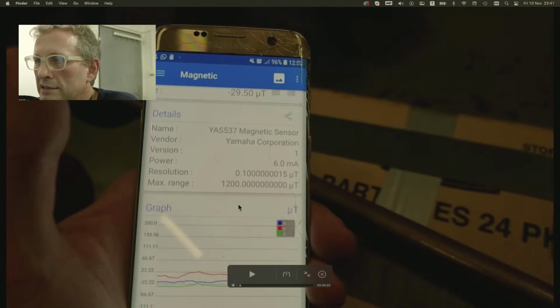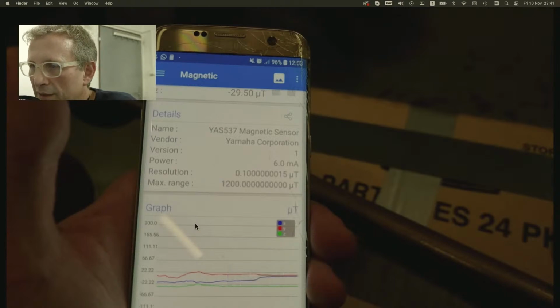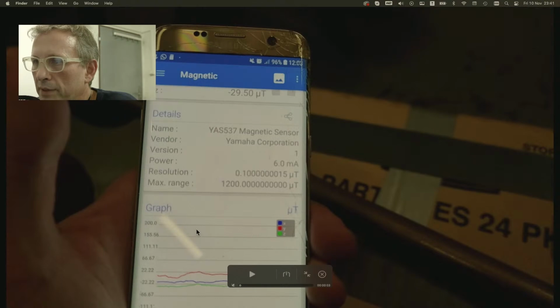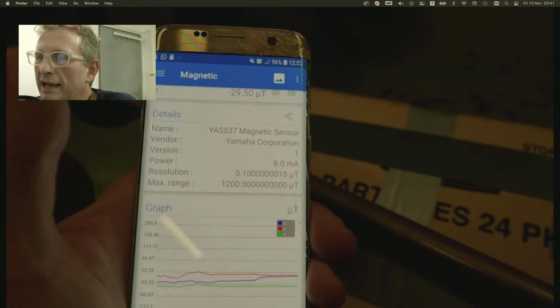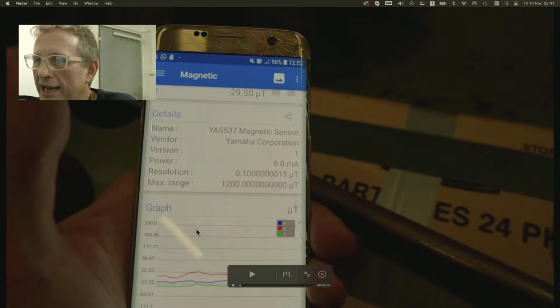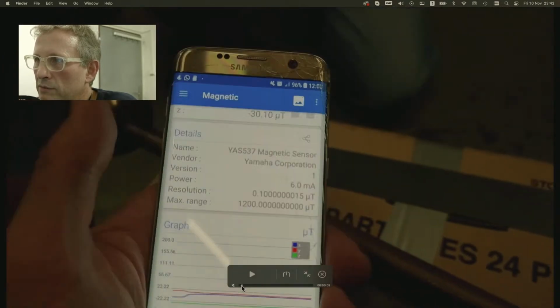But I'm using this free tool called Sensors Multi-Tool, and so for replicators I would suggest that you do not take a magnet to your device until you have done a rough profile of what's going on magnetically, because if you have any variation in thermal expansion coefficient with stainless steels, you could end up finding that you have some ferromagnetic areas being created, and if you then run a magnet over them, you will actually magnetize those areas, and that may even affect the way the device performs. So it's very important to establish what the magnetic nature is before you go ahead, and then before you ever get a magnet near it again, you want to see what magnetization has occurred. And this is where it gets a little bit interesting, which I'll talk about in a little while.